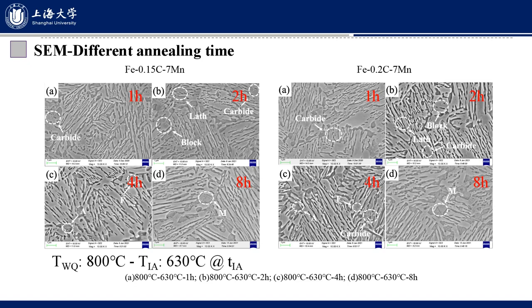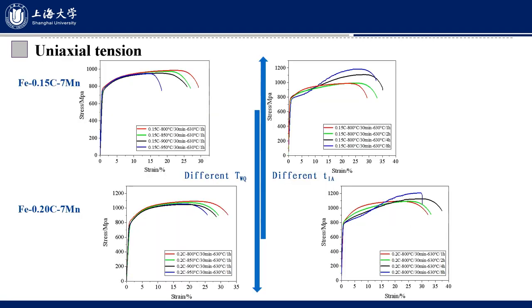This slide shows the microstructure of the steels intercritical annealed for different times. For the 800 degrees C water quenching condition, for the intercritical annealing temperature of 630 degrees C case, this is the microstructure of the steel with water quenching first and intercritical annealed at 630 degrees C with different annealing times. This slide shows the mechanical property of the steel for different water quenching conditions and different intercritical annealing time conditions.